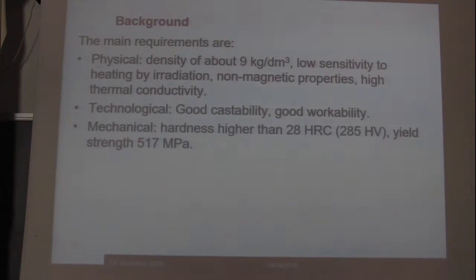So, as you can see, the choice is not really an easy task, because we have several requirements. We have physical requirements, so we need a density of about 9 kilos per cubic decimeter, low sensitivity to heating by irradiation, because the temperature of the satellite must be kept quite low. It must have no magnetic properties and high thermal conductivity.